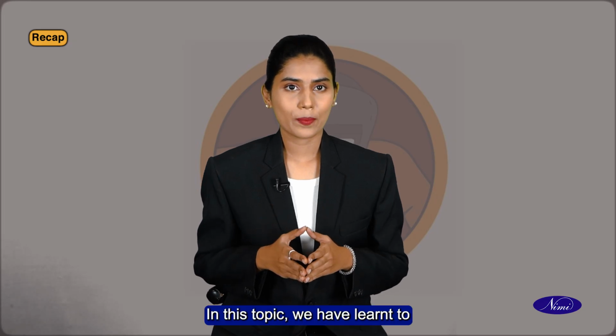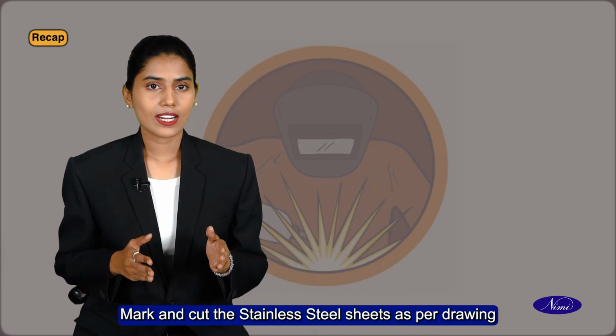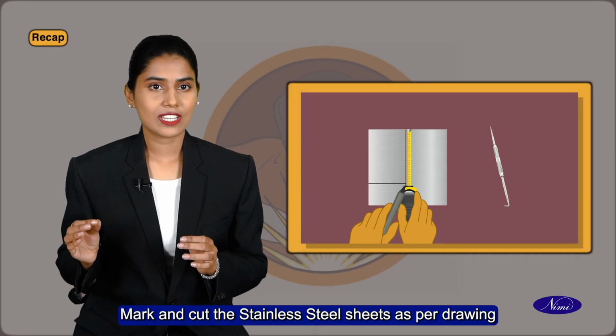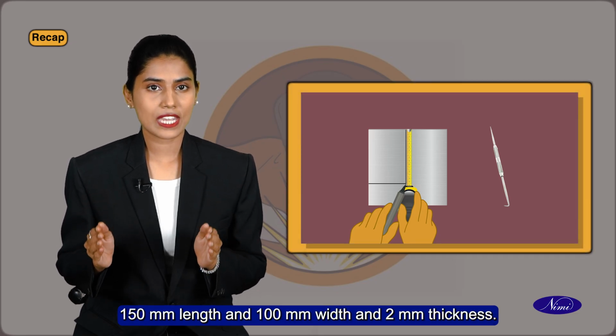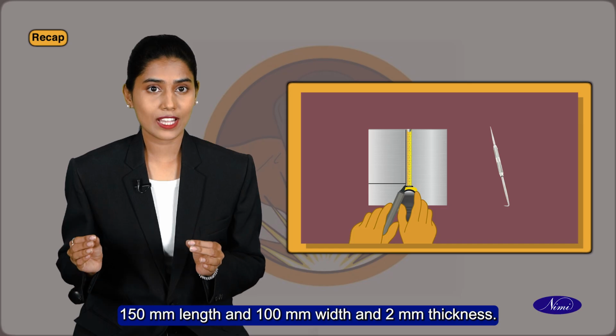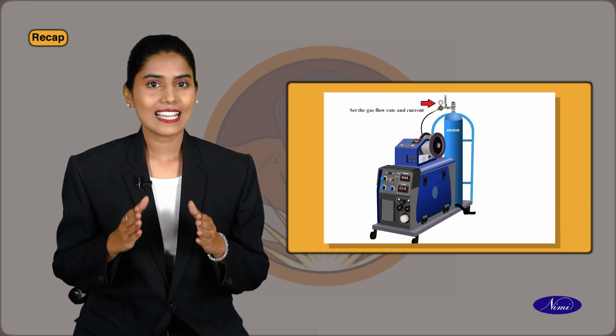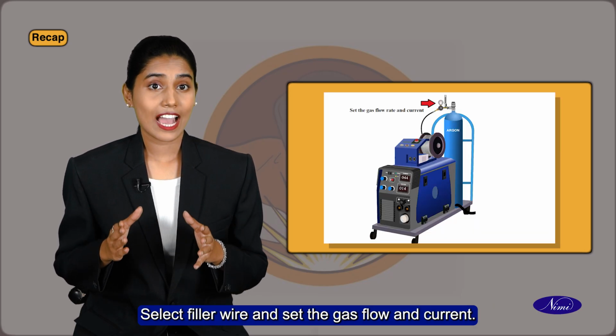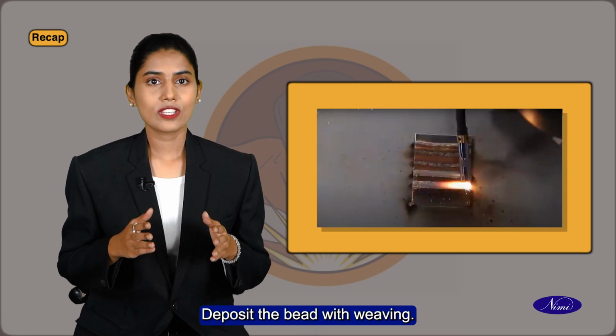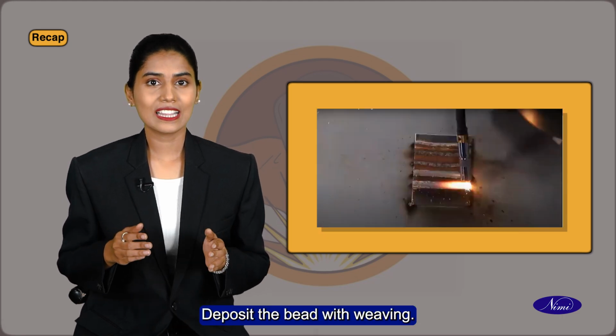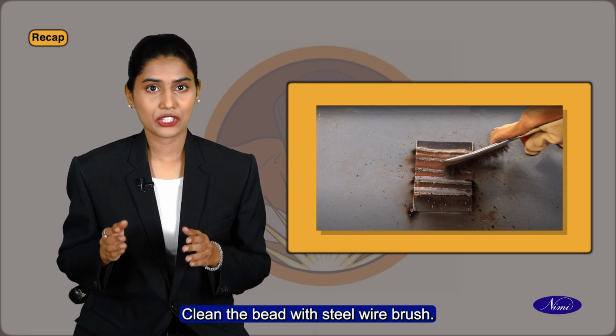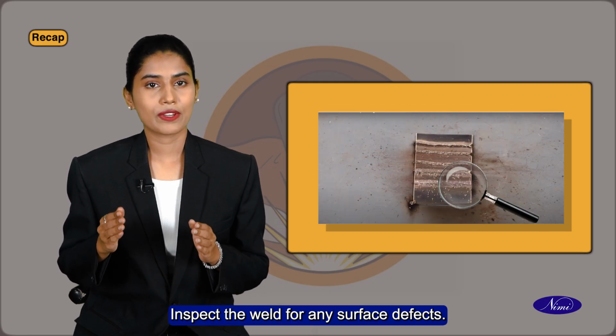Recap. In this topic, we have learned to mark and cut the stainless steel sheets as per drawing, 150 mm length and 100 mm width and 2 mm thickness. Select filler wire and set the gas flow and current. Deposit the bead with weaving, clean the bead with steel wire brush. Inspect the weld for any surface defects.